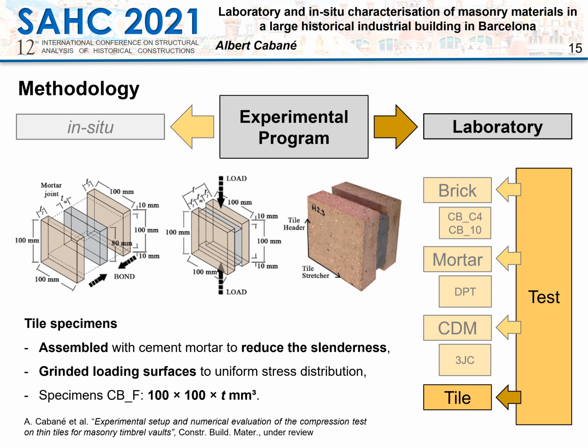Finally, a new methodology for testing thin clay tiles was developed. This methodology overcomes the problem arising from their limited thickness in the loading direction. For this purpose, a new specimen assembled from two clay tiles was proposed. Testing the assembled specimen instead of the single tile allowed the reduction of the slenderness during the compression test.